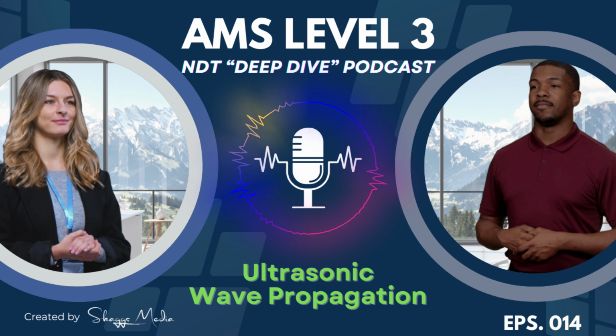This energy loss isn't linear. It's typically measured by an attenuation coefficient, and it causes the wave's amplitude to decay exponentially as it travels further. That's why for really thick parts or materials that are highly attenuative, like some composites or cast metals, you need powerful transducers and maybe lower frequencies. Otherwise, the signal just fades away into the noise before it gets back.